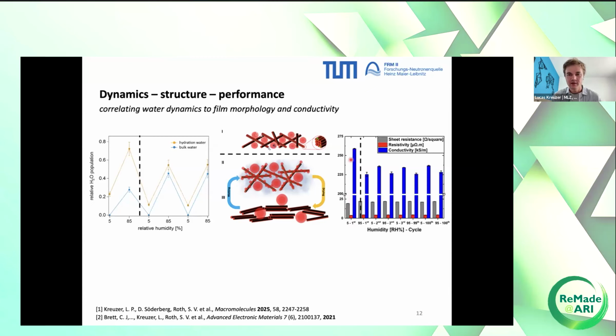In the very first initially dry state, we have the highest conductivity. And this corresponds to this nanomorphology. This corresponds to this ratio of hydration and bulk water. If we humidify the system, the conductivity decreases. We are in this state. We are in this water ratio. This drop in conductivity we attribute to the dewetting of the PEDOT:PSS.